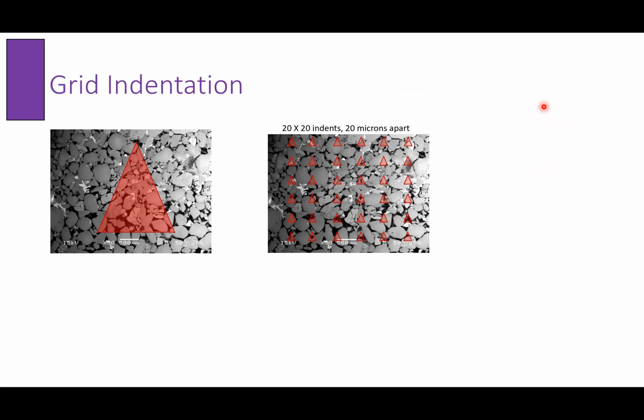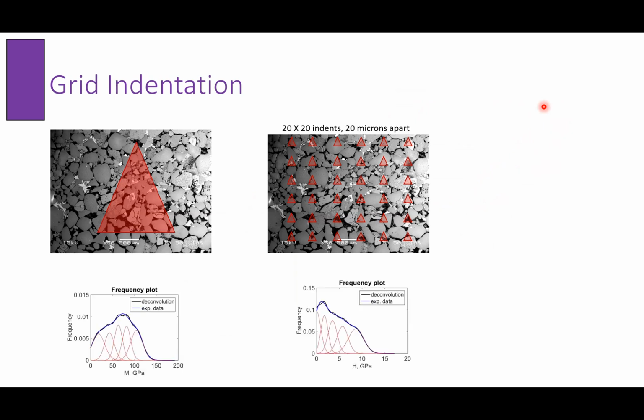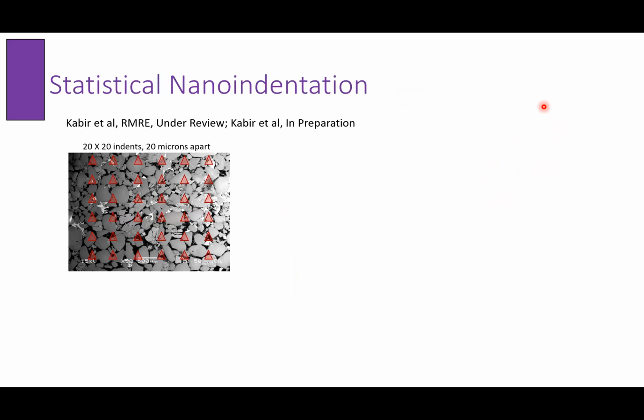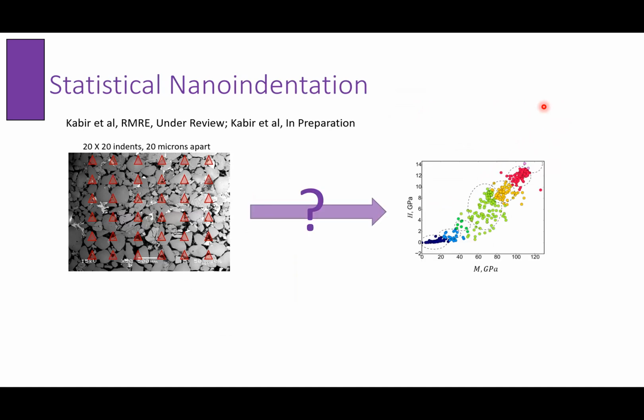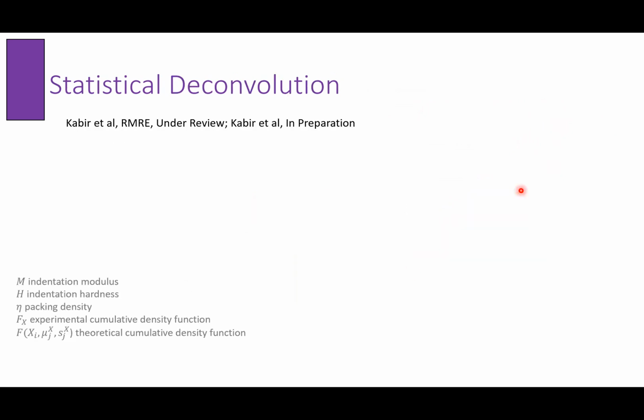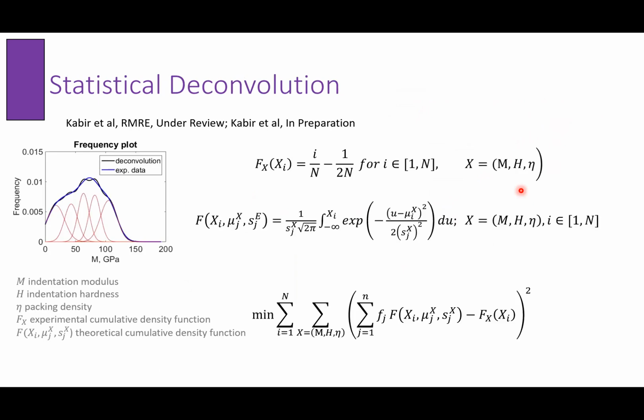Now we extend this nanoindentation to go to grid indentation. So with grid indentation, instead of having just one large indent, we're going to have a series of small indents. And usually we like to have it in a grid, for instance, 20 by 20. The idea afterward is really to use machine learning, in this case a statistical deconvolution method, to be able to identify different chemomechanical phases based on their mechanical signature. The idea, at the end, is to be able to represent this distribution of the indentation modulus or indentation hardness as a weighted sum of Gaussians, where each Gaussian is going to represent a specific chemomechanical phase within the material.